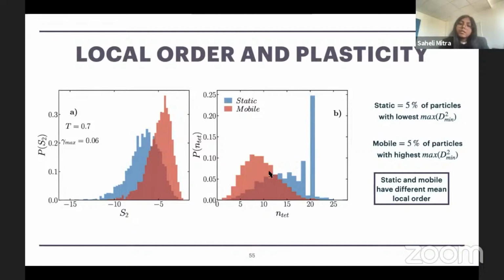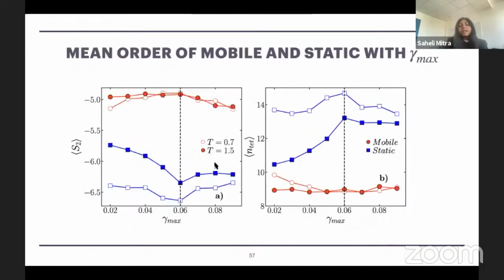Interestingly, we see from the distribution of tetrahedrality that in the case of static particles, there is an abundance of Ntet equal to 20. In fact, we might remember that this value of tetrahedrality equal to 20 is related to icosahedral clustering. That means particles with tetrahedrality equal to 20 are reluctant to move as we are shearing our system. Now, this is an example plot for one particular temperature and one particular shear amplitude, and we repeat this for all the samples we have, and we plot the mean values of S2 and Ntet for mobile and static particles for all the gamma max values across yielding. What we see is that the mobile particles consistently, for all the gamma max values, have lower structural order, lower Ntet or higher S2.